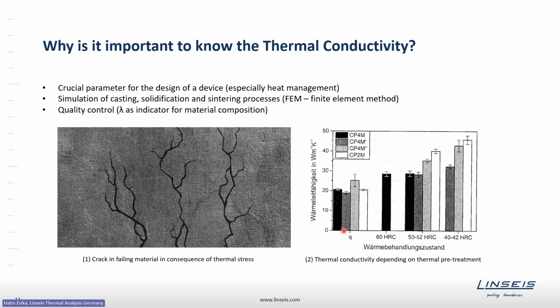Here is an example where you can see a material where the thermal conductivity depends on the thermal pretreatment. So you see different classes of material and different pretreatments, where you see thermal conductivities ranging from 20 to about 45 watt per meter Kelvin, just due to different processes. Additionally, the thermal conductivity is also an indicator of quality. So if you want to build in a material with a certain thermal conductivity to have good heat management, then you of course need to guarantee that this material really has this estimated thermal conductivity. So this is also useful for quality control.